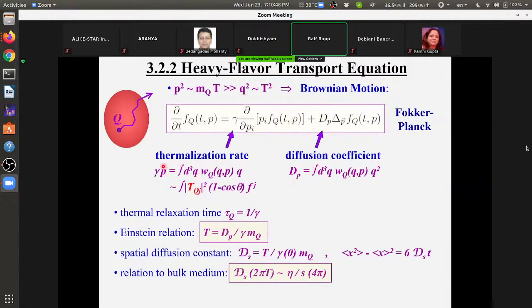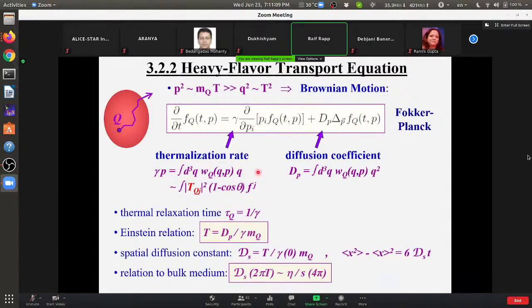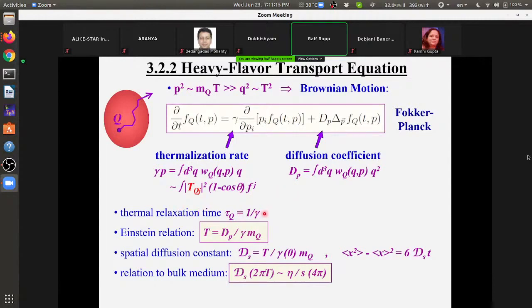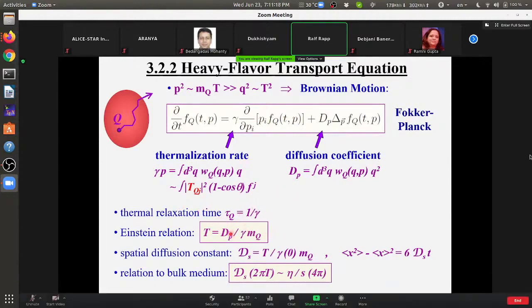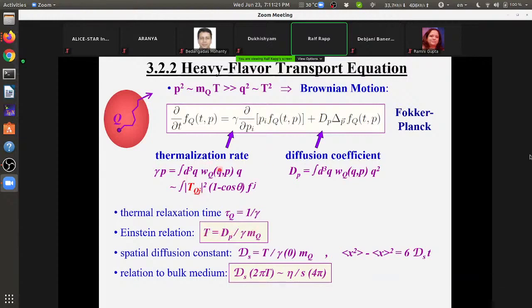Both of these coefficients, momentum diffusion and thermalization rate, are at the fundamental level related to the heavy-light quark scattering matrix, a two-body scattering matrix element weighted with an extra angular factor which makes it a thermalization rate and not a scattering rate. The scattering rate is larger because it counts every scattering, but for thermalization you need quite a few scatterings to thermalize the heavy quarks. The thermalization rate is related to the relaxation time, just the inverse. There's this very important Einstein relation between the two coefficients to make sure you're really reaching the equilibrium limit, so their ratio nicely gives the temperature - a beautiful relation.